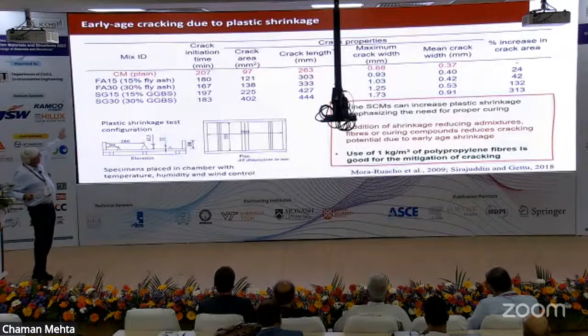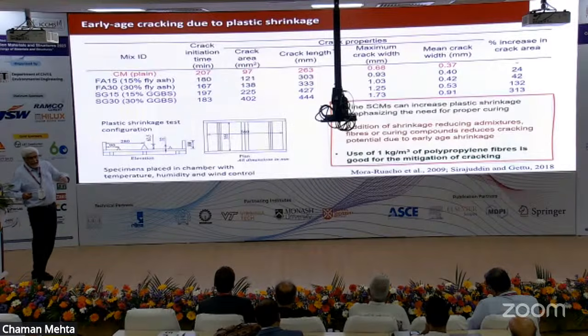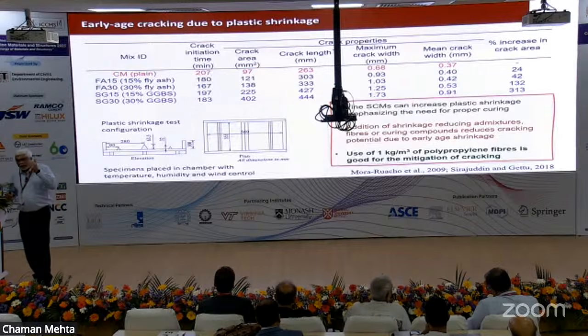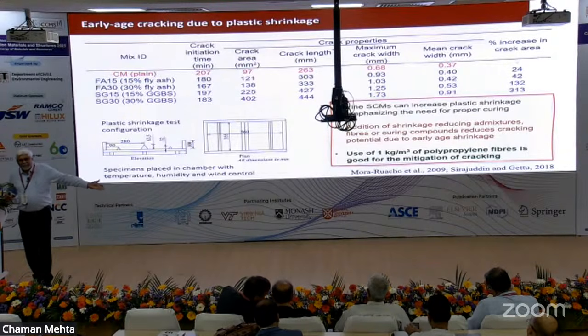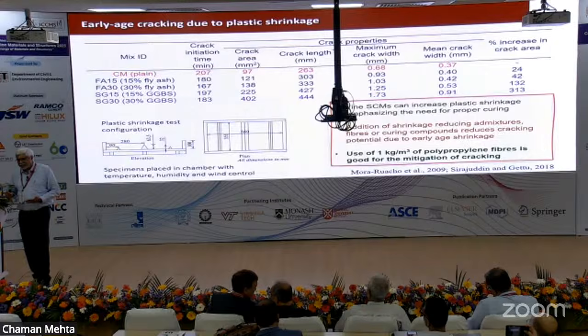The fly ash content is 15-30%, GGBS is 15-30%. Cracking increases a lot. The strength is the same, workability is the same. From the structural engineering point of view, it is the same concrete. But the material has changed and now it's going to crack. And this crack will stay forever in the structure.